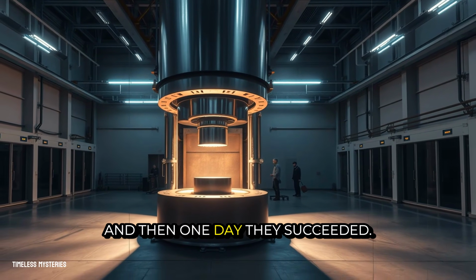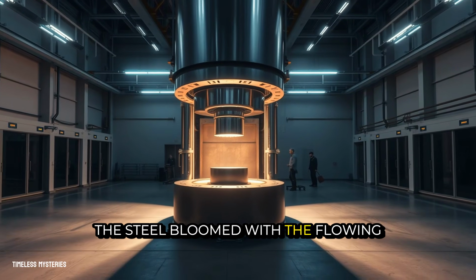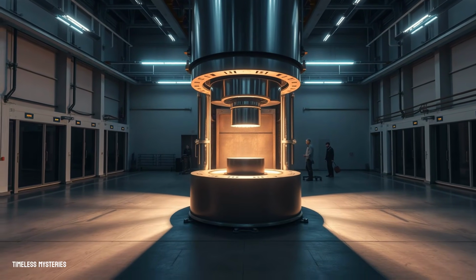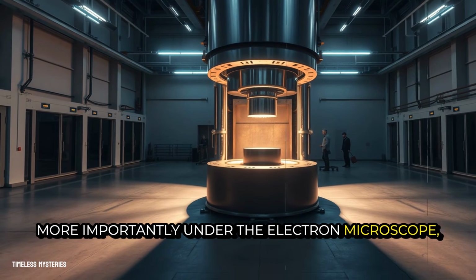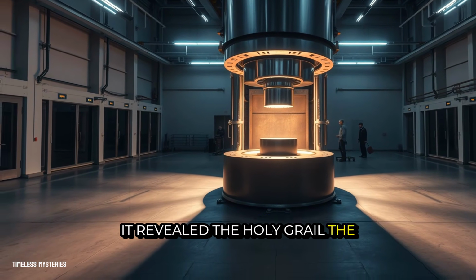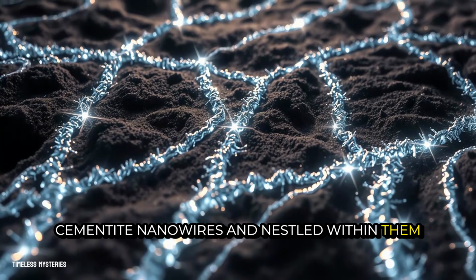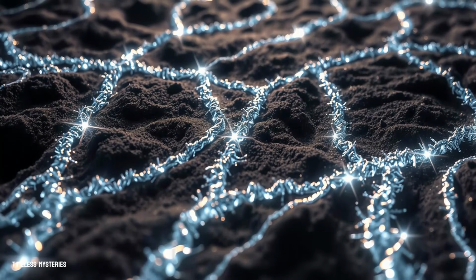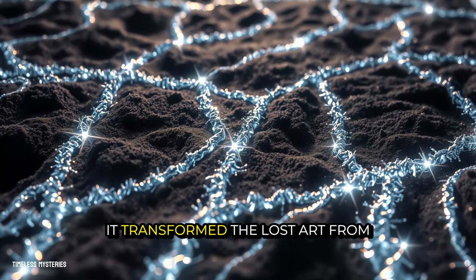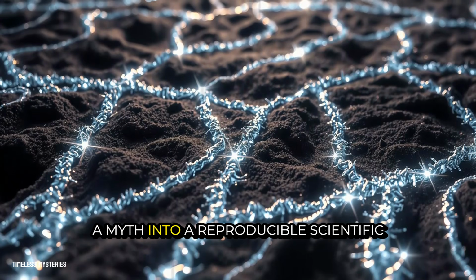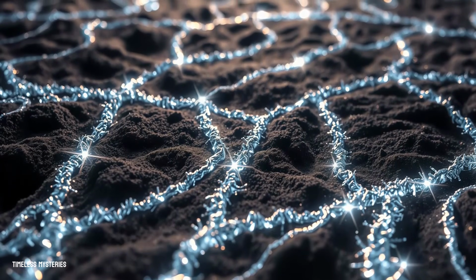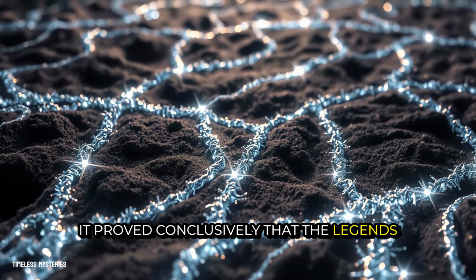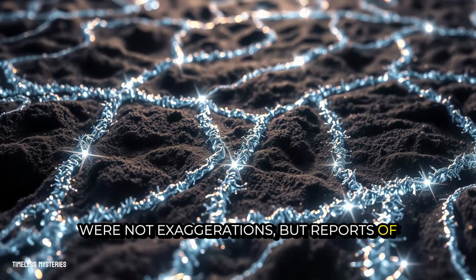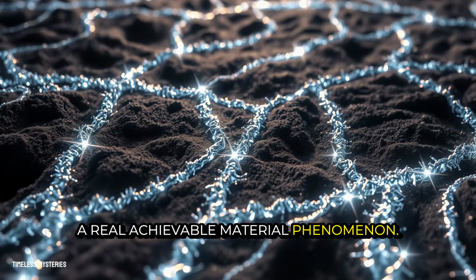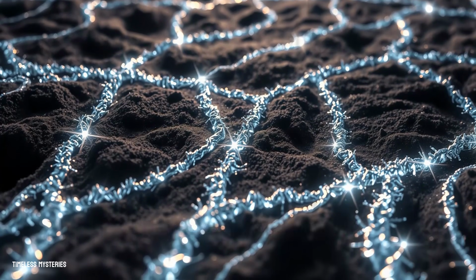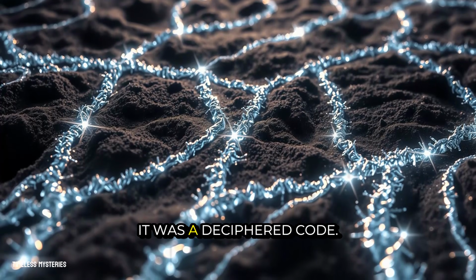And then, one day, they succeeded. The steel bloomed with the flowing, watery damask pattern. More importantly, under the electron microscope, it revealed the holy grail, the cementite nanowires, and nestled within them the carbon nanotubes. This was a monumental moment. It transformed the lost art from a myth into a reproducible scientific discipline. It proved conclusively that the legends were not exaggerations, but reports of a real, achievable material phenomenon. The process was no longer a black box of mystery, it was a deciphered code.